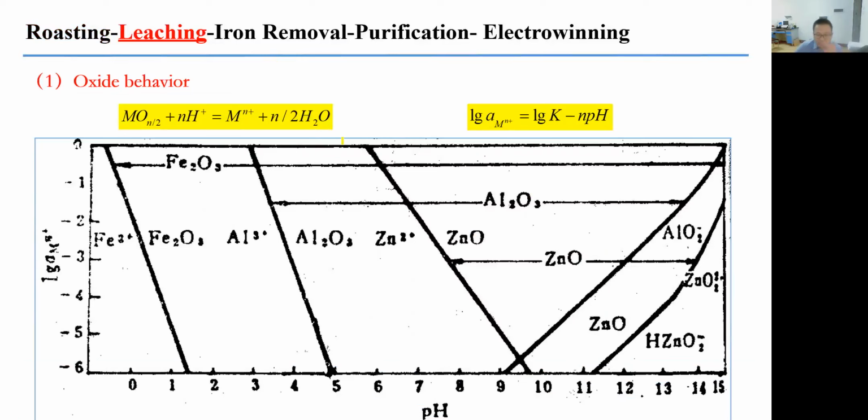When we have knowledge about the roasting process, we know the presenting form of the calcine. It mainly consists of zinc oxide, and some copper oxide, lead sulfate, and zinc ferrite. There are also some gangue components and products of some other impurity elements.